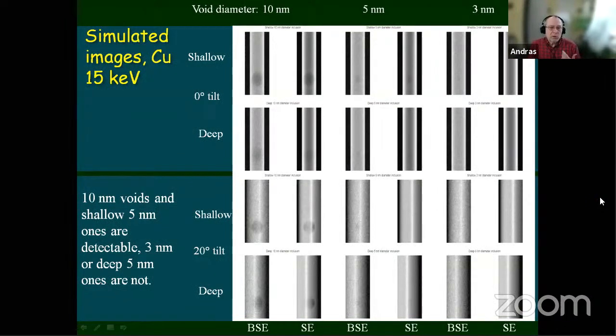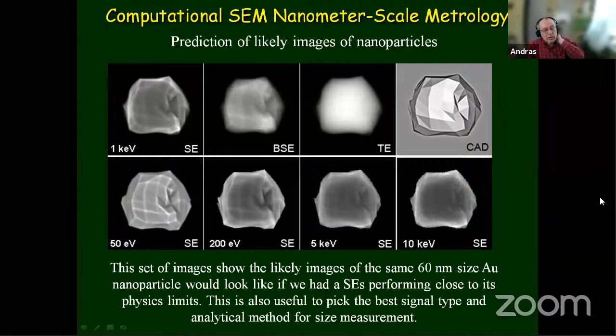Here is something where you can use the simulation and the modeling to predict likely results. So these are copper structures with a void in them. And we looked into it through modeling, what the chances are to detect them and what size you can still detect. And you can see, down to some of the small sizes, we can see even 5 nanometer size voids inside a copper line. And whether backscattered or secondary signal is better to use for this, it depends. And again, what landing energy and other things. So this allows you to predict the results, calculate what you are supposed to get. And that could be very powerful for being able to measure something. You can choose the imaging parameters better. Next slide, please.